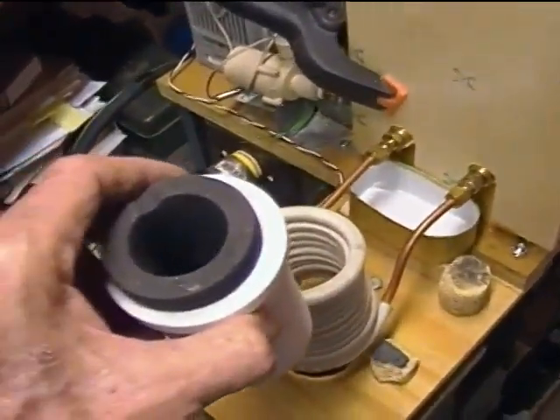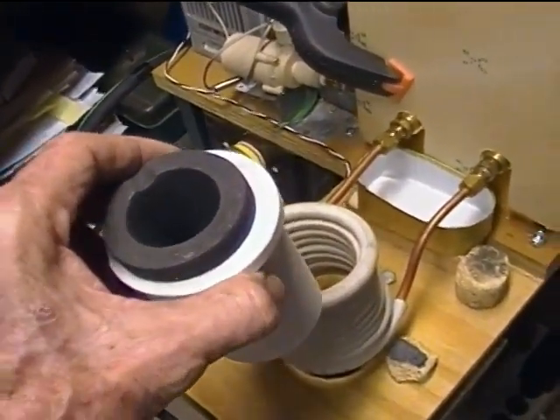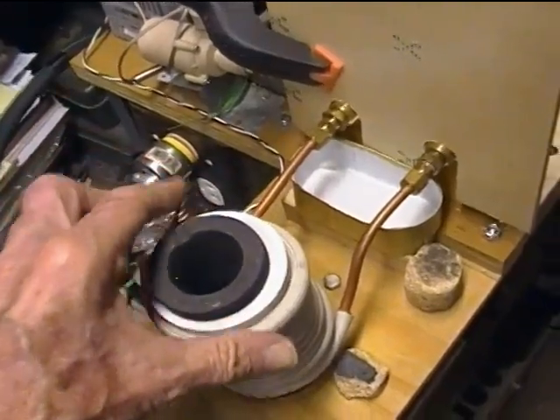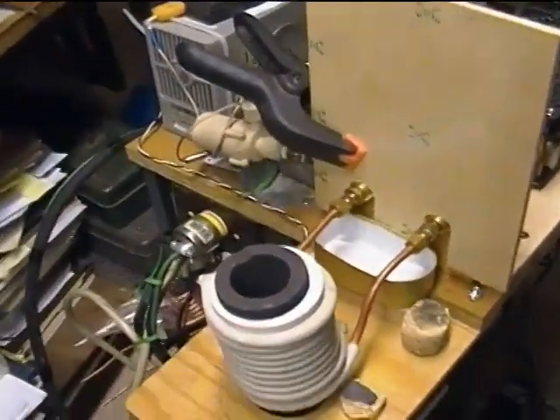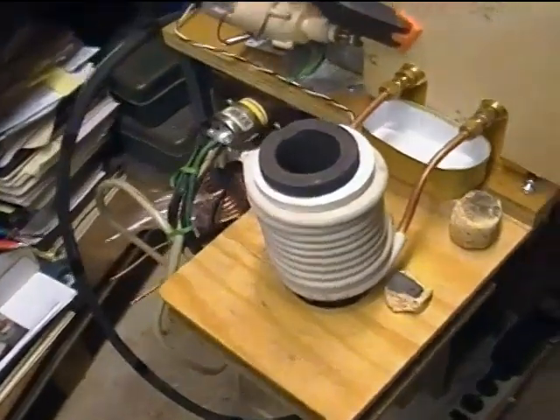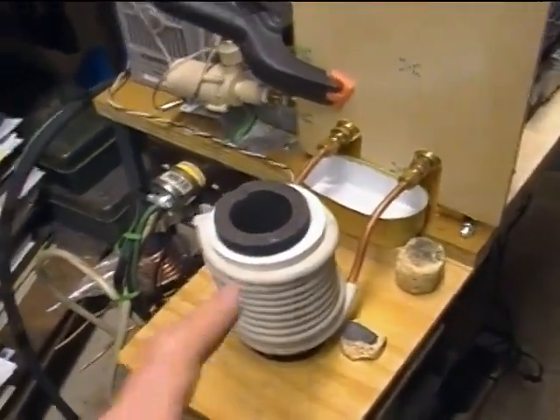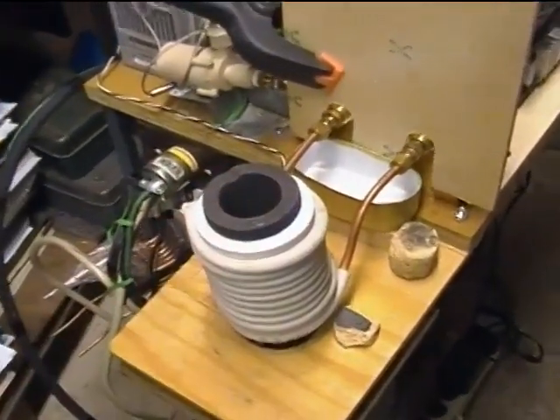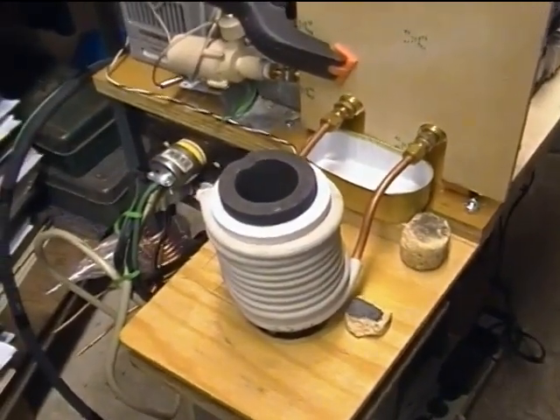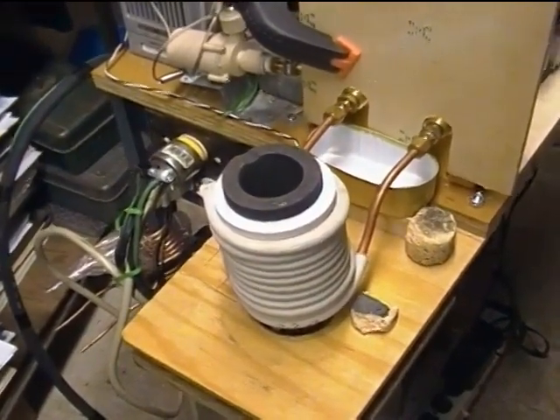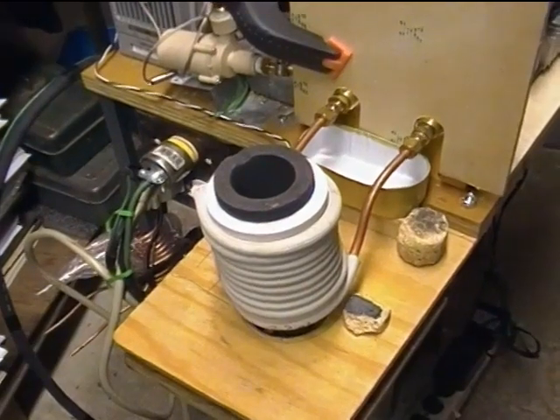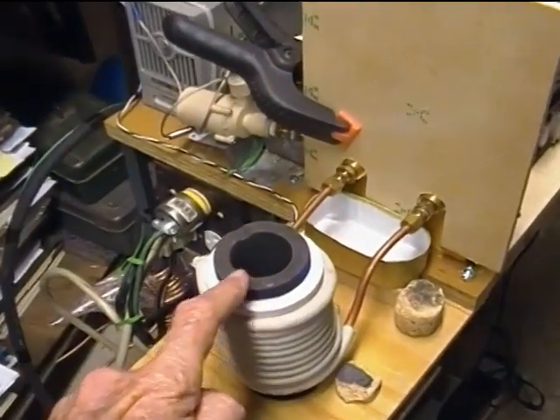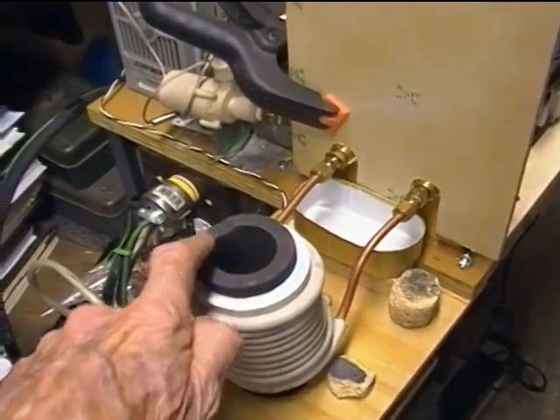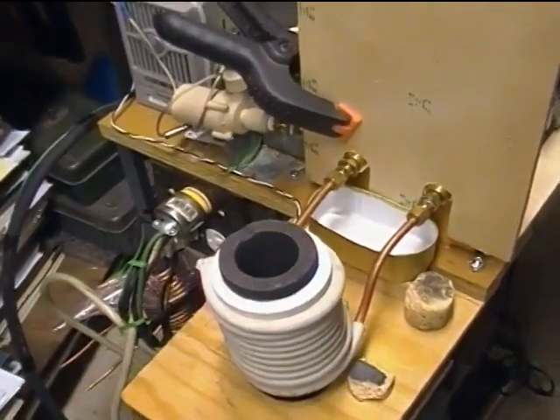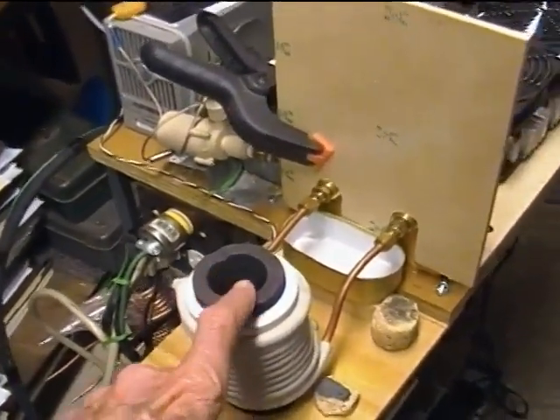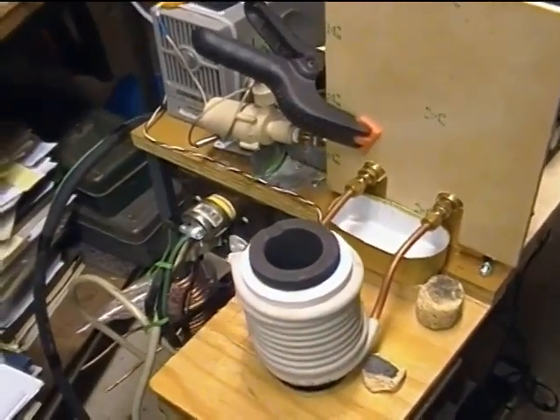So normally what I've been doing when I'm melting copper is I drop the crucible all the way into the work coil, and maybe I'll get currents close to 45-50 amps with a fresh thick-walled crucible when I'm melting copper. And that current actually goes down some just as the copper melts. Then if I'm using a crucible which is worn, it becomes thinner and thinner every time you use it, then that current will drop off another 6 or 8 amps.